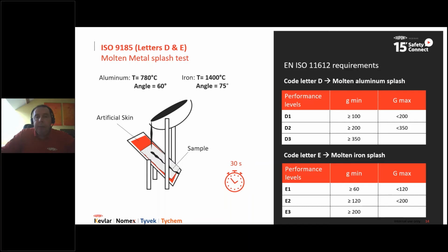And then you take a new piece of fabric, a new piece of artificial skin, and you do the same test, but this time with 200 grams of molten aluminium splash. If you pass this, you have the level D2, and you go to the 350 grams that you're splashing onto your Nomex. However, if you fail the level D2, meaning if after having poured 200 grams of molten aluminium onto